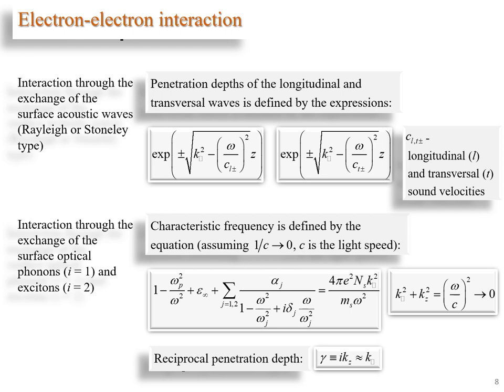These are acoustic phonons of Rayleigh type at the surface, or Stoneley type at an interface, polarized normally to the surface, consisting of the longitudinal and transversal parts, linked by the boundary conditions, and possessing the respective penetration depths. At higher frequencies, there are interface polaritons of optical phonon type and exciton or hybridized plasmon-exciton type. Their dispersion and penetration depths in the actual short wavelength region may be deduced in quasi-static approximation from the following equations.